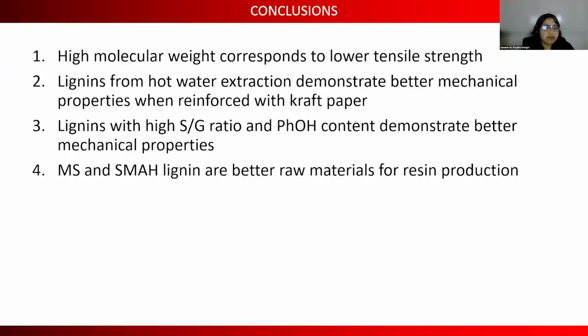So lignins with high SG ratio and high PHOH content, and relatively low molecular weight, are ideal for resin preparation. And overall, sugar maple and miscanthus lignins are better raw materials. And the reason being is that both of these had high SG ratio and high PHOH.